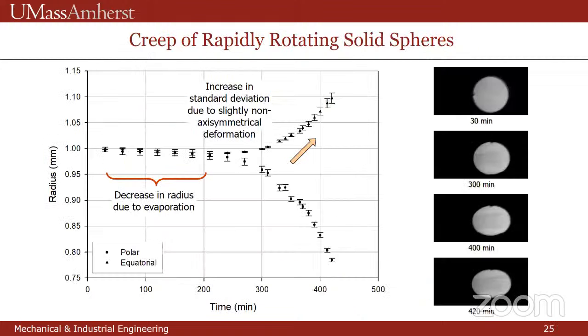What we did was to take a 2 millimeter sphere and spin it. It turns out if you spin it at 30,000 revolutions per second, 2 million RPM, you get 100 megapascals shear in the center. And then you can heat it up and watch it deform. And you see that creep occurs here. So in this case, we were accelerating the sample very slowly by photon pressure. This is a pure niobium sample at 1985 degrees C, the same temperature and material as the previous plot. And after about 5 hours, the deformation becomes noticeable. And after about 7 hours, you get the end result there on the bottom.